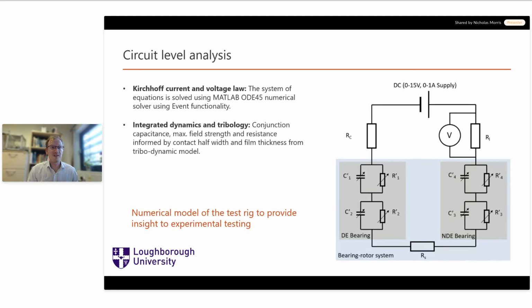So we solve this as a nonlinear time varying RC circuit. Why is it time varying? Because these capacitances and resistances change with the film thickness. So as the film thickness changes, those electrical properties also change. So it's coupled in just one direction. The other thing that we also consider is the resistance of each of the contacts, so this is the contact between the outer race and rolling elements, and then this is rolling element to the inner race, and drive end and non-drive end bearing. And this is the resistance of the shaft in between.